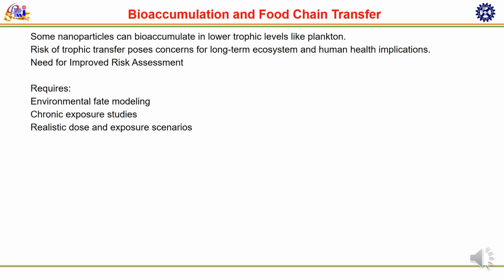Bioaccumulation and food chain transfer. A nanoparticle can accumulate in an organism if its uptake rate exceeds elimination. Key factors are surface charge and size, which influence cellular uptake; solubility, since soluble nanoparticles release ions and increase persistence; and surface coating, which may slow or accelerate clearance. Accumulation occurs in specific tissues, and food chain transfer follows.